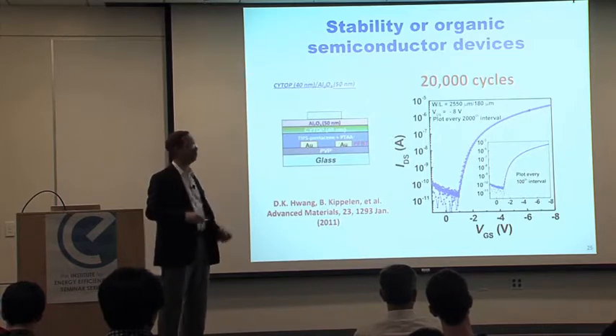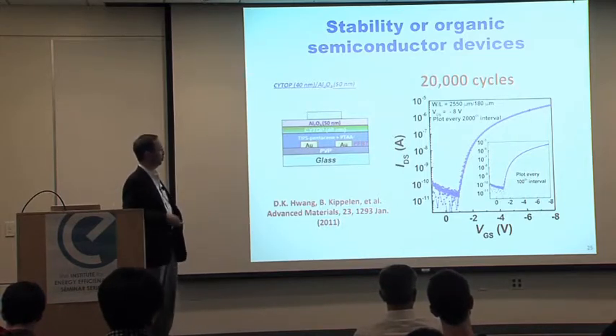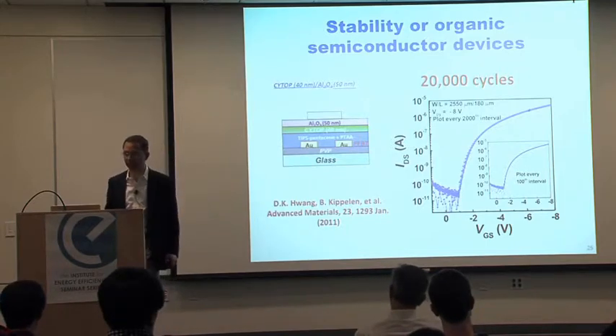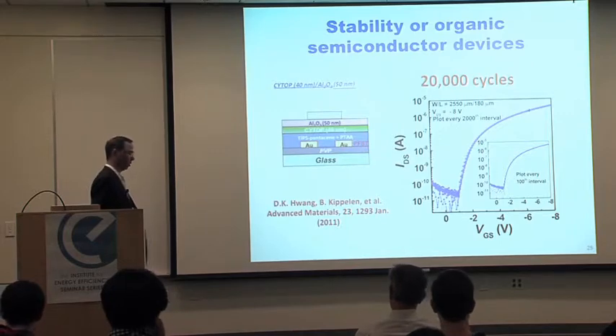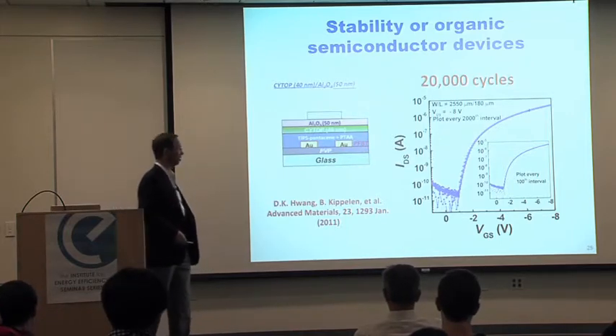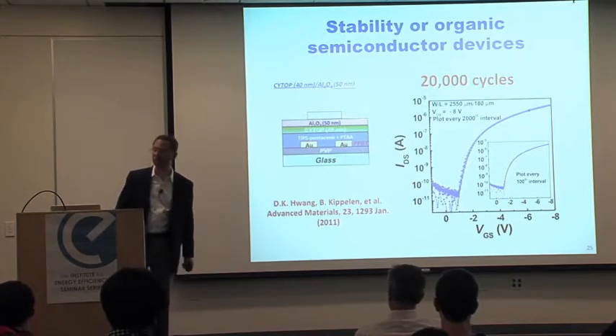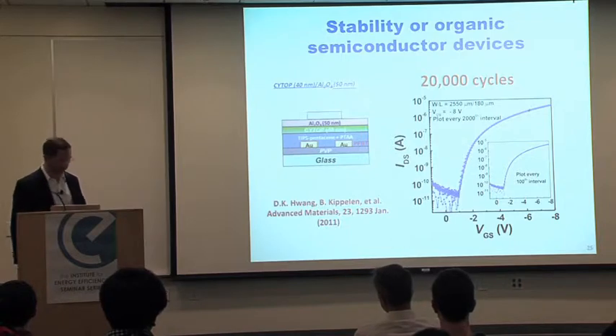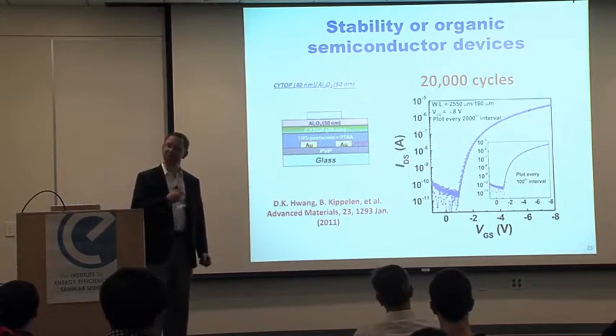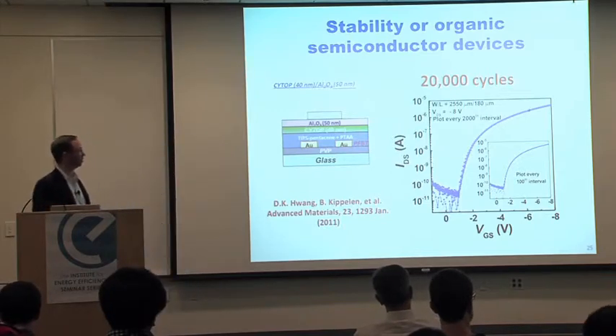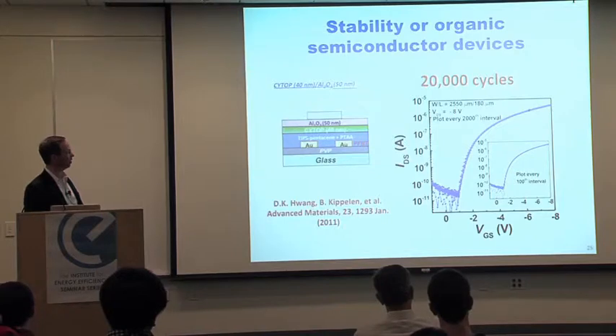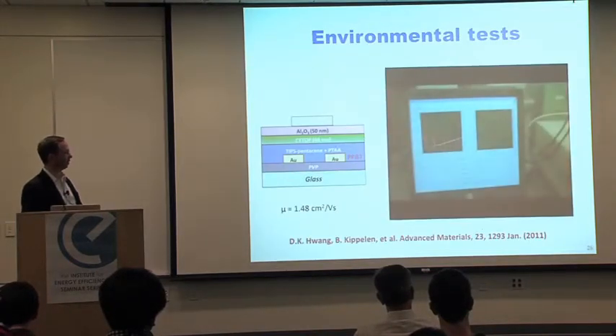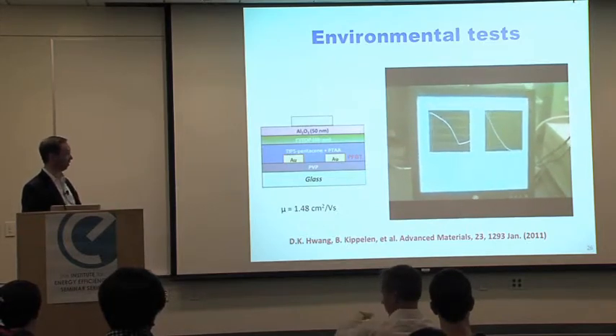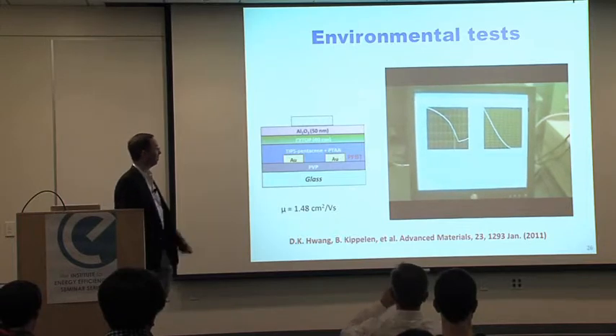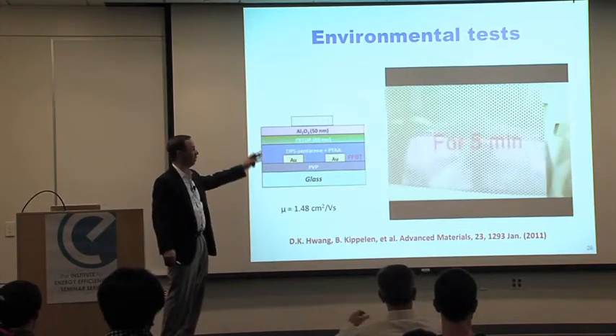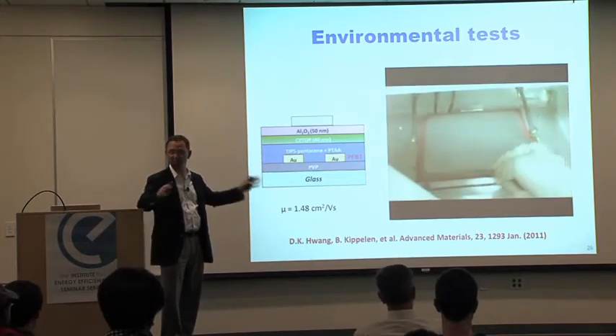They're also very stable under continuous operation. These devices were sitting just like this in the lab, and Do-Kyung, my postdoc, every week would put them back in the semiconductor parameter analyzer and measure the transfer characteristic, and he didn't see any change. So at some point, he started to be really impatient. He said, okay, I'm going to beat these devices really hard. And so the first treatment was pretty dramatic. He took these devices, which had been fabricated 11 months ago, after characterization, and put them, like shown here, with no additional packaging or anything, into a plasma chamber for 5 minutes. Say, okay, this is going to do these samples in, right?